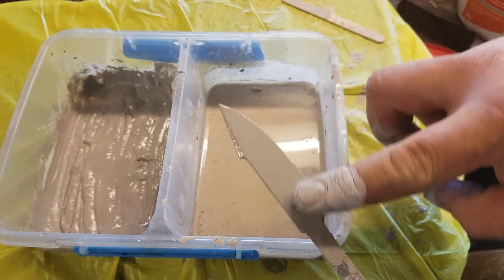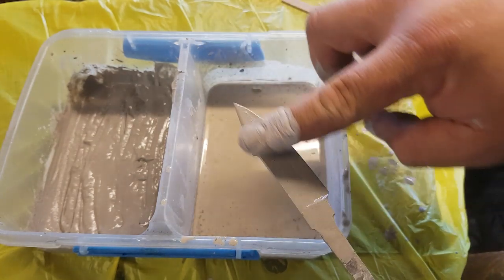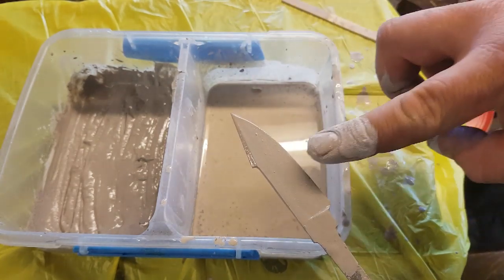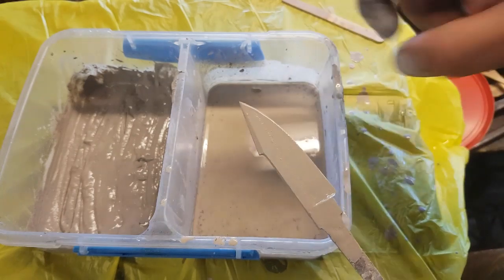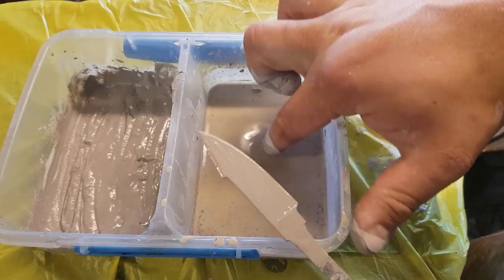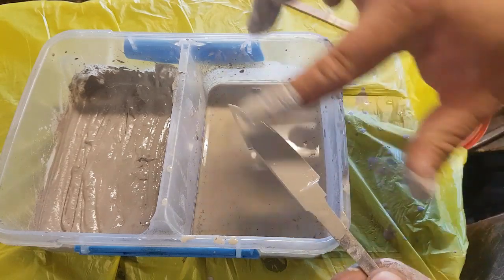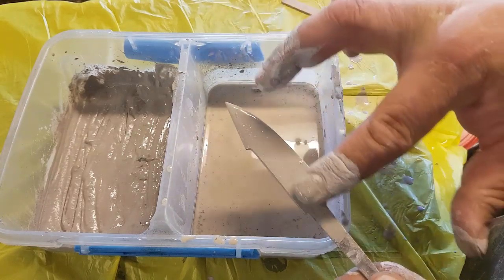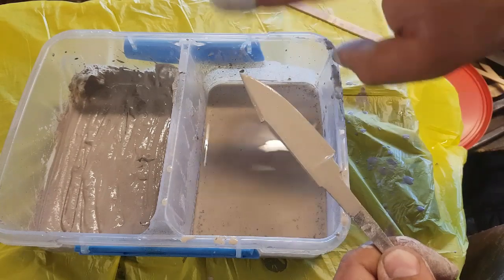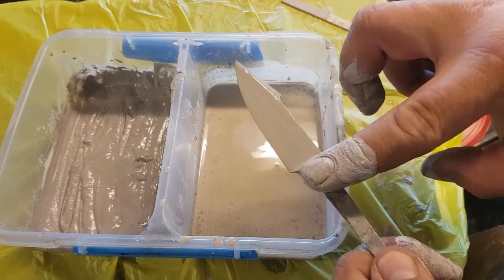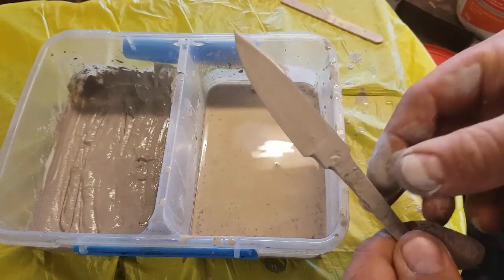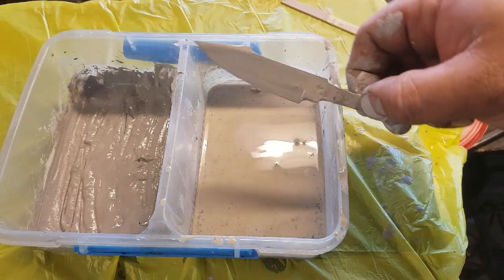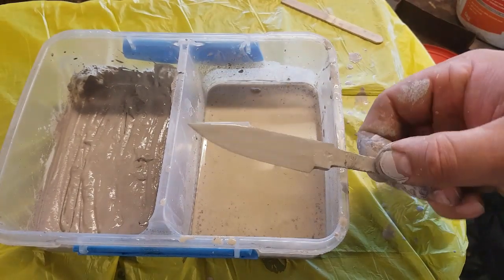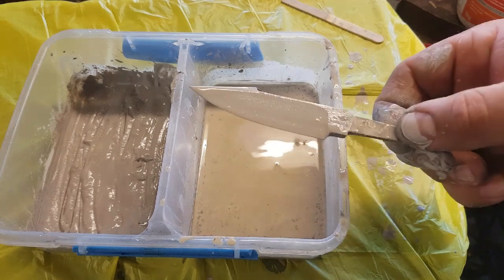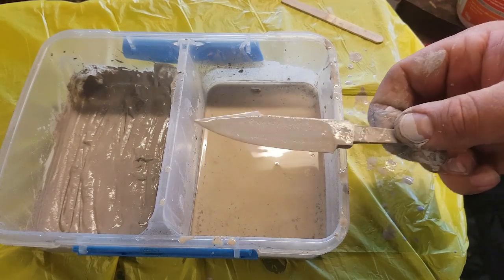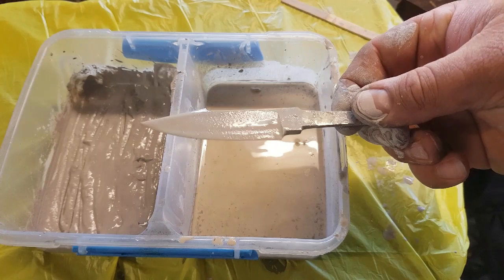So what I got to do now is allow this to dry, and then once it's dry, it will act like the wire in a wire Hamon, where you use baling wire or something to hold the Hamon clay on. This will provide that tacky surface for the Hamon clay to stick to. The advantage of this one over the Hamon wire is that you don't have that bulky wire creating thick lumps, and therefore you can get much finer detail in your Hamon.